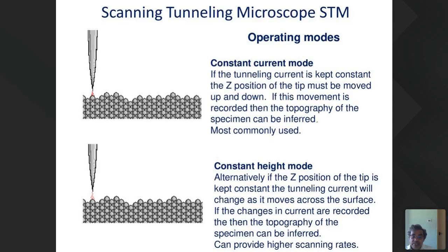Alternatively, the height position of the tip is kept constant. That means you are going to maintain the height. The tunneling current will change as it moves across the surface, with respect to the varying distance between the tip and the specimen surface. The changes in current are recorded, and then the topography of the specimen can be inferred. This can provide a higher scanning rate compared to the constant current mode.